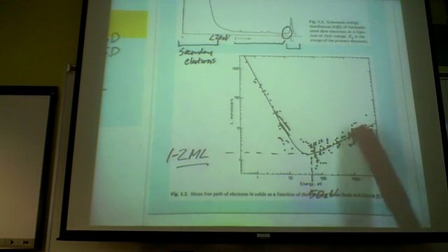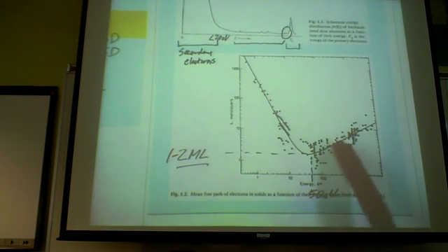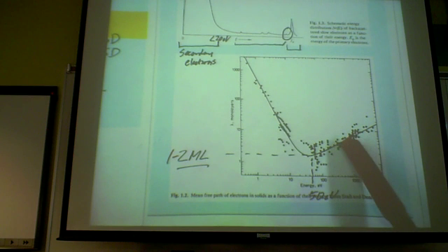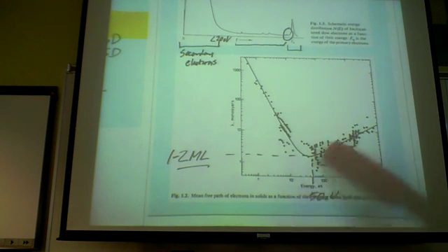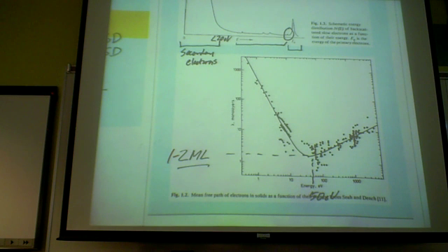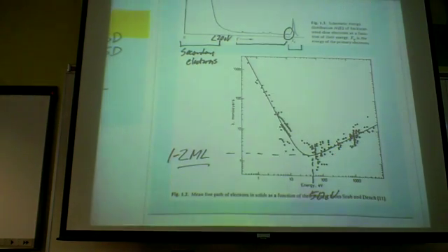If you use a high energy electron beam, then the electron could come out from deeper in the surface. So in order to optimize and get the most surface sensitivity, you should use 50 to 70 electron volt. Anything else, you would have not as sensitive, because these have a higher mean free path.